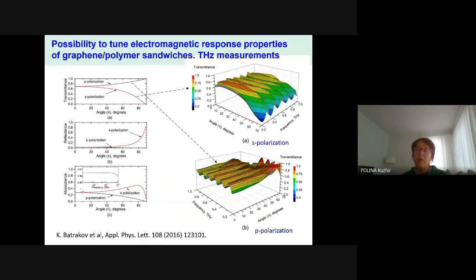And this is exactly what we observed experimentally. This experiment was done for graphene placed on top of a 0.5 millimeter silica substrate. You see that for the S polarization wave, you could observe the transmittance change from 70% to almost zero when you change the incidence angle from normal incidence to quite oblique, close to 70 degrees.